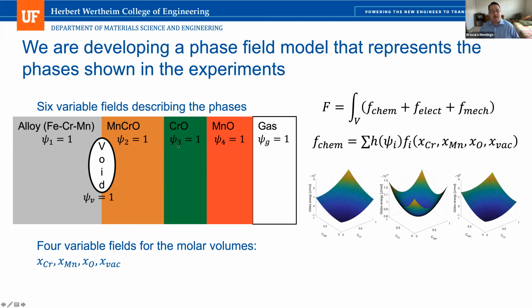And then the evolution of these variables are defined by partial differential equations that are functions of derivatives of the overall free energy of our system. So it's trying to lower the free energy over time. And so we define the free energy as a function of all of these variables. So we have a chemical part of the free energy, and we're taking that information from thermodynamic databases and making some approximations. So we can have a free energy curve for each phase. And then we also need to include the electric energy. So we need to have the impact of the electric potential, because this is an electrochemical problem.